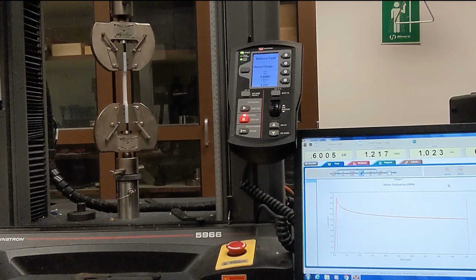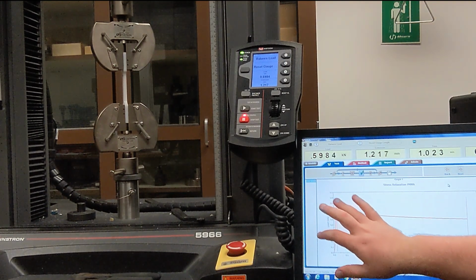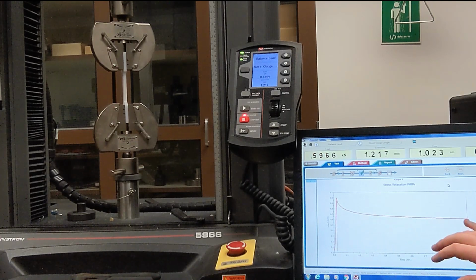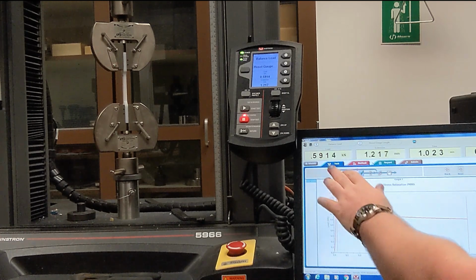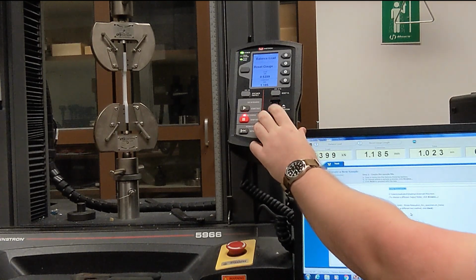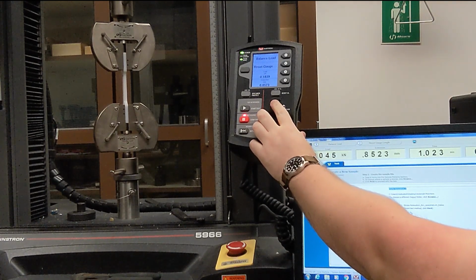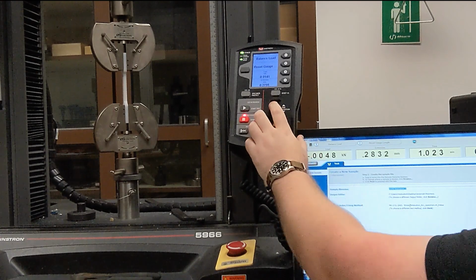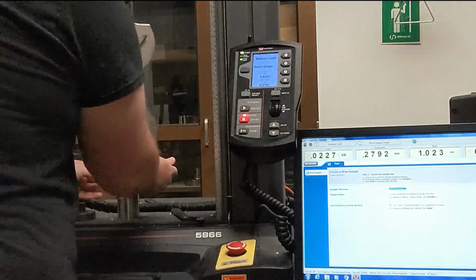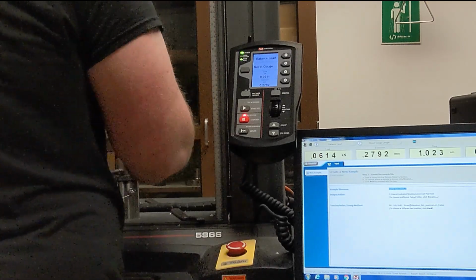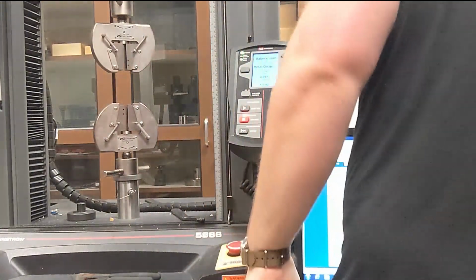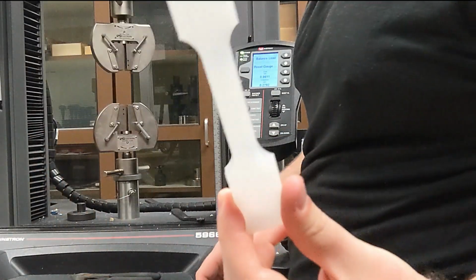You can't really read these numbers, I'm sorry, but we went from 1 kilonewton initial load. When we stopped, we were right at about 600 newtons. So we dropped about 40% over time. And it's actually still dropping even though the test is stopped. All right, so we're going to take this sample out. Okay, we're going to put in the LDPE sample.